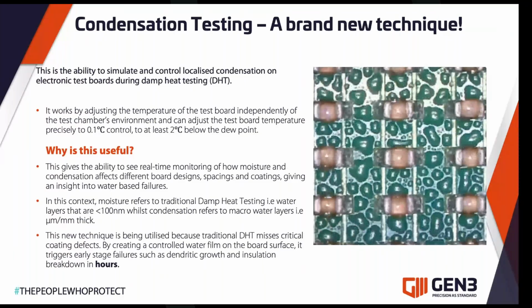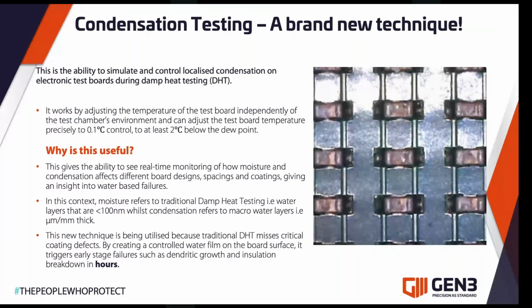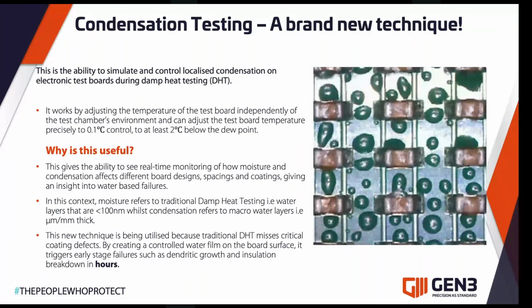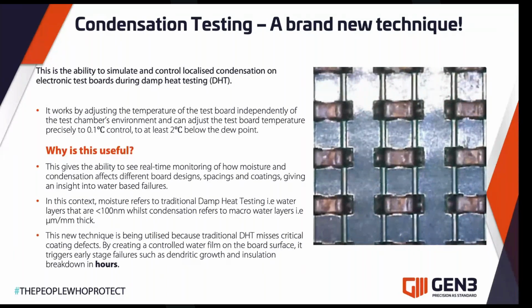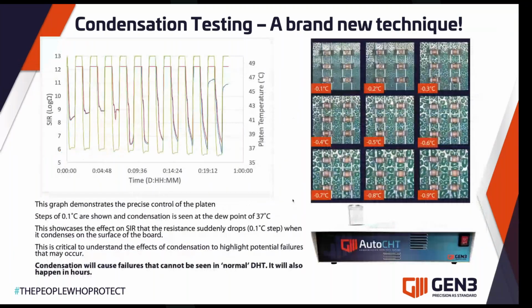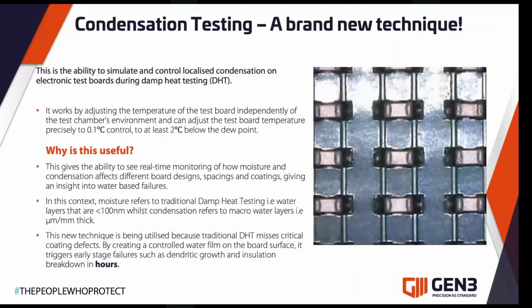So why is this useful when talking about SIR? This gives the ability to see real-time monitoring of how moisture and condensation affects different board designs, spacings, and coatings, giving an insight into water-based failures. When I mention moisture, what I'm referring to is traditional SIR damp heat testing, so water layers that are less than 100 nanometers thick, whilst condensation refers to the macro water layers, i.e. microns to millimeters thick. This new technique has been utilized because traditional SIR damp heat testing can miss critical coating defects. By creating this controlled water film on the board surface, it can trigger early stage failures such as dendritic growth and insulation breakdown, most importantly in hours, not weeks.